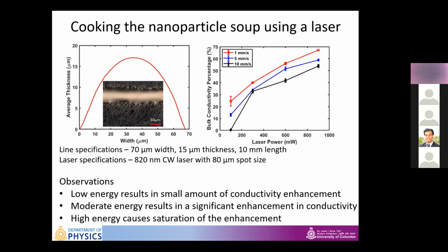In other words, the conductivity increases with increasing effective laser energy, meaning that the x-axis is in power, but since it is associated with the moving speed, you can calculate an effective energy. So with the effective energy, if you increase it, the conductivity increases as well. If you reduce the speed, the conductivity increases again because the effective energy increases.